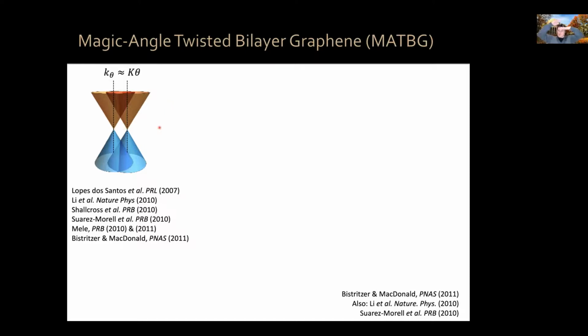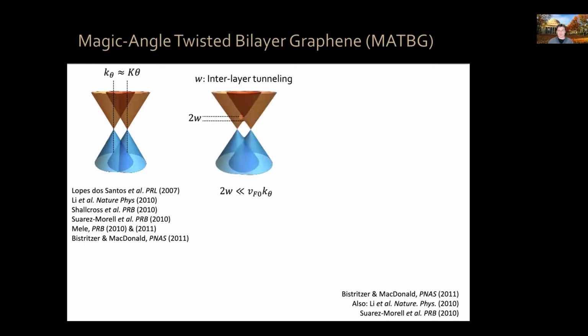because when we put graphene on top of graphene, these 2 graphene sheets are just spaced by 3 angstroms, electrons in one graphene sheet are very much aware that the other graphene sheet exists. In particular, they can tunnel between the 2 layers. And that leads to this bonding, anti-bonding type of states at this crossing energy. This is very similar to bonding, anti-bonding states in a hydrogen molecule, but for a gigantic graphene molecule.